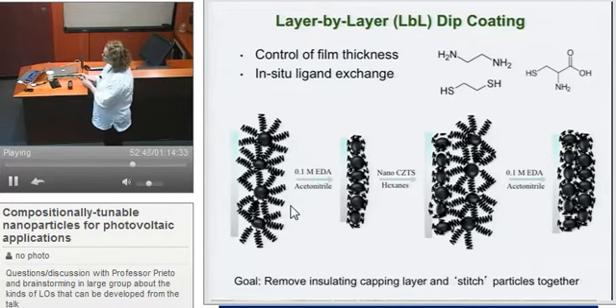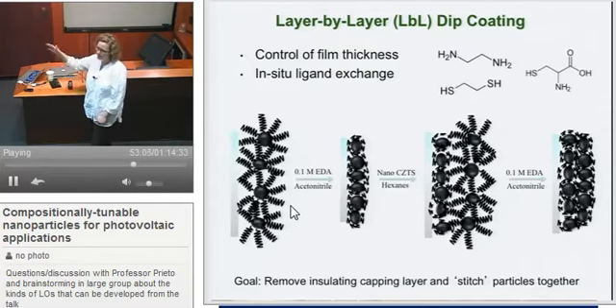So you stitch the particles together, then you dip again, and you make another layer, and then you dip again. In this way you build up the film. It's called layer by layer dip coating. It's one method to make films. We used to have undergrads that did this. But the films we want to study as a function of thickness, which can correlate to how many times you dip, and the films that turn out to be the best have to be dipped somewhere between 100 and 200 times, and that is not a good use of trying to teach an undergraduate research.